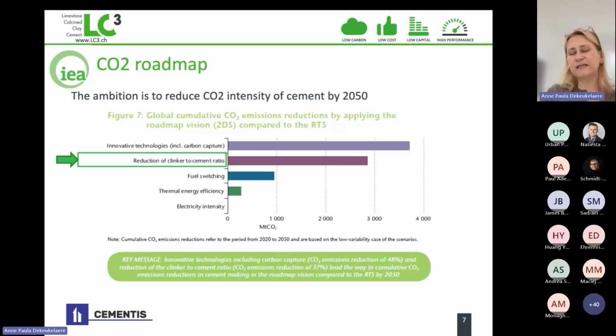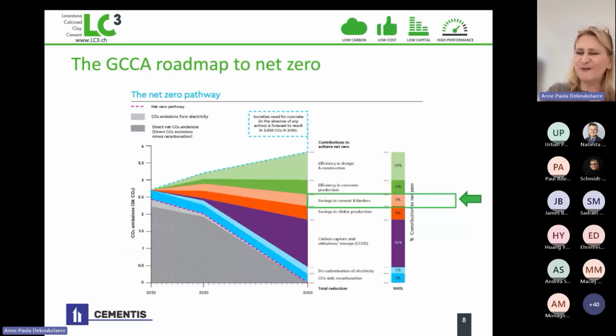So I will show you here 2 different roadmaps. One from IEA, where they also emphasize part of the lever to decarbonize is the reduction of clinker to cement ratio. So the reduction of the clinker into the cement, as Paul said, is the element that is the highest CO2 intensive. And I will show you also the GCCA roadmap, where the line savings in cement and binders, that's where the clinker factor will have to decrease and be replaced by other materials.